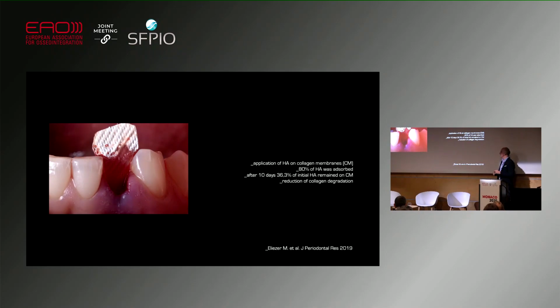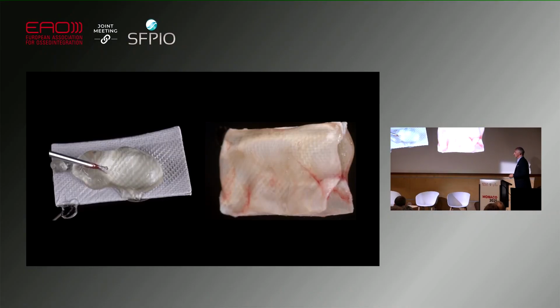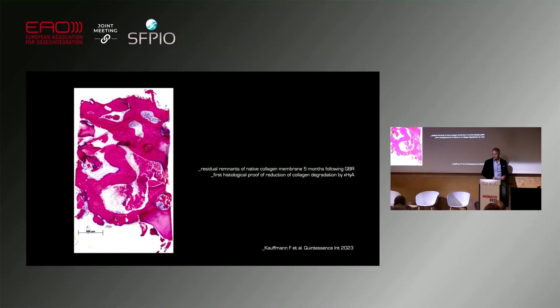And by that we see a reduction of the collagen degradation, so we see a longer standing time of these membranes. This is also a nice finding, a nice add-on for us as clinicians. So what we do is we soak these membranes with hyaluronic acid, and we have the evidence that it stays there and it helps us with the collagen degradation.